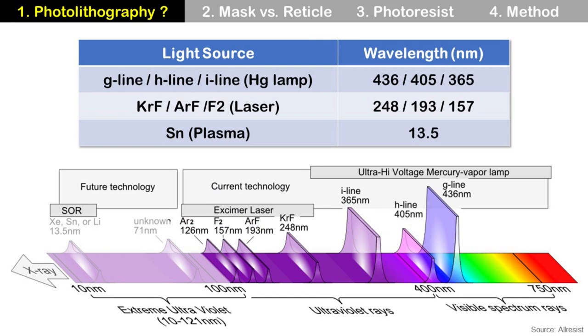There are several kinds of light sources, and light with shorter wavelengths can make smaller semiconductor patterns, meaning more complex semiconductor chips. The first type uses a Mercury lamp: G-line at 436nm, H-line at 405nm, and I-line at 365nm. The second uses lasers: Krypton Fluoride at 248nm, Argon Fluoride at 193nm, and F2 laser at 157nm. The third uses tin plasma at 13.5nm for EUV lithography.